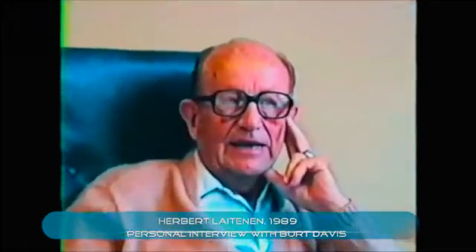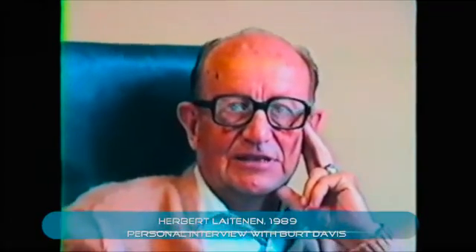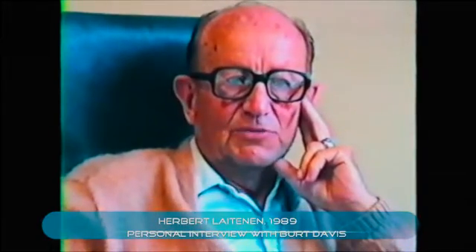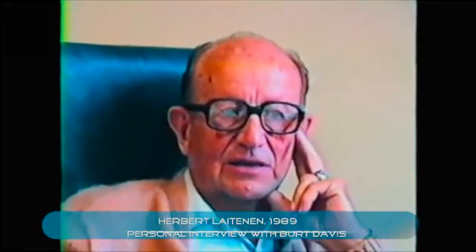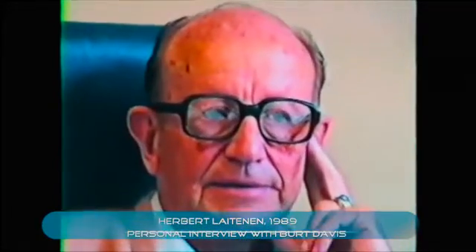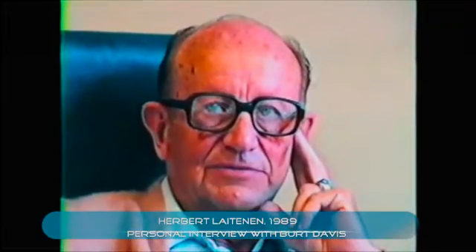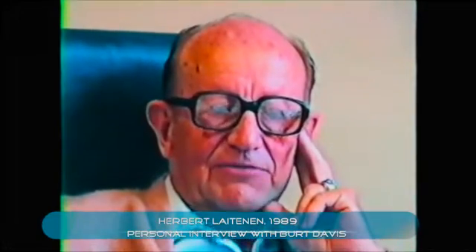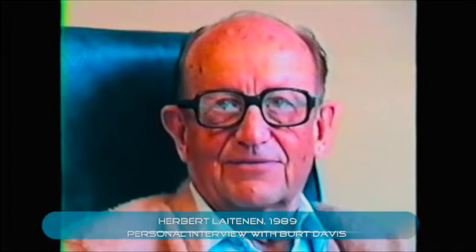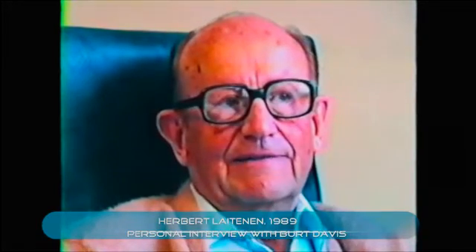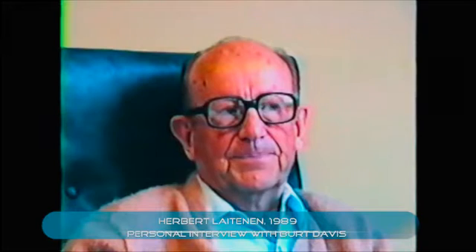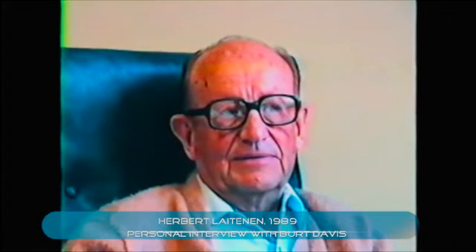So we were searching for something better. And I had heard about infrared reflecting glass, which is electronically conductive. This was commercially available, so we started with that. One of the immediate problems we found was that if we ever went cathodic enough to generate hydrogen on it, we lost the whole layer of tin oxide. It was reduced, and we later proved it was reduced electrochemically to metallic tin. But it disappeared. And so then we gradually were trying to make our own.